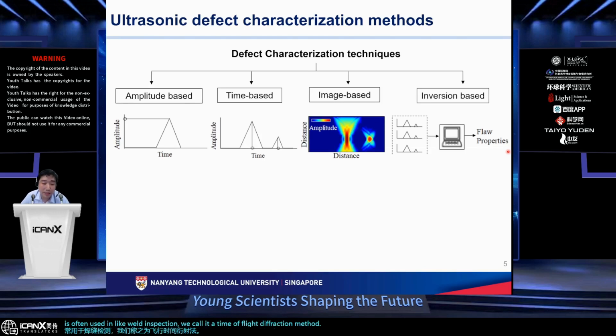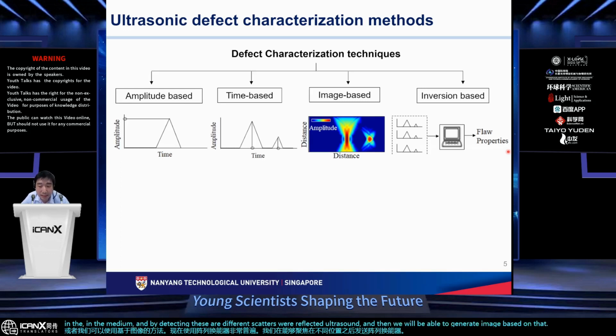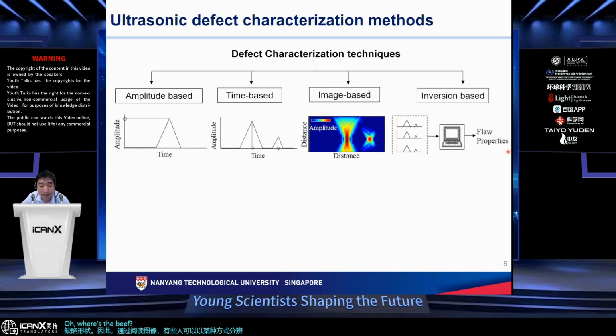Or we can use an image-based method. It's very commonly used nowadays with array transducers. We send signals from an array transducer, and after beamforming, it's able to focus at different positions in the medium. By detecting the ultrasound reflected by these different scatterers, we can generate an image based on the defect position and defect shape. So by reading the image, some people can tell where the defect is and how big it is, right? So that's the image-based method.